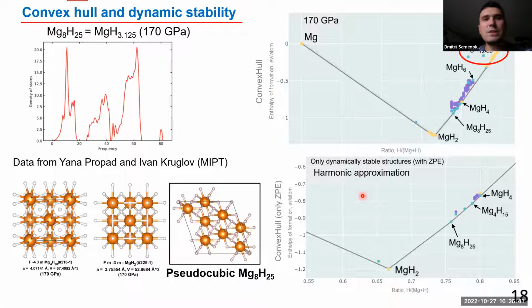Okay. And we tried to explain it in a different manner. We tried to recalculate to get again the theoretical convex hull. We used USPEX calculations, and we extended the calculations to bigger unit cells with the number of atoms up to 100 atoms of magnesium and hydrogen together. We found a lot of other compounds with non-stoichiometric composition, which lie close to the convex hull, especially when we exclude dynamically unstable compounds. And one of the candidates is magnesium 8H25, which is dynamically stable.